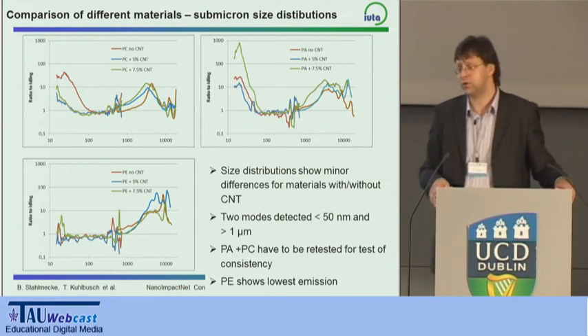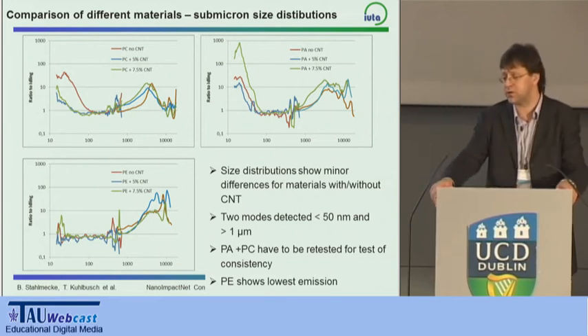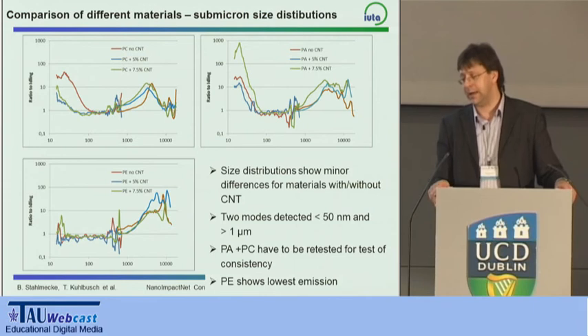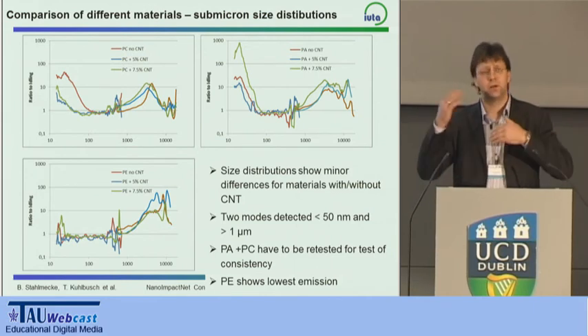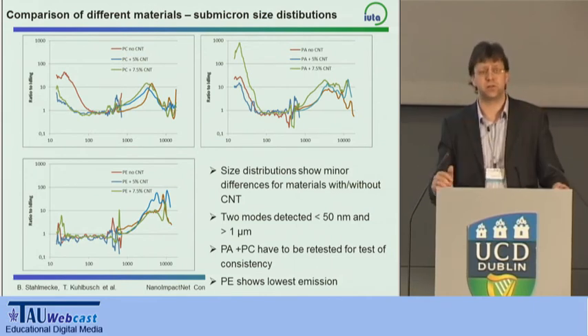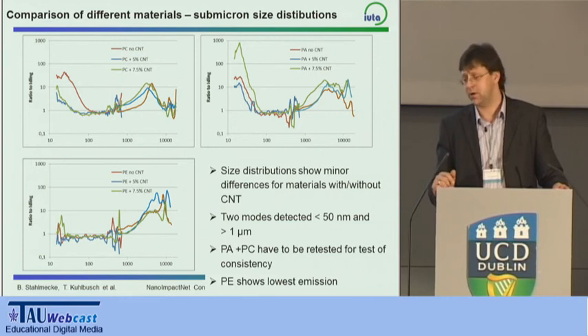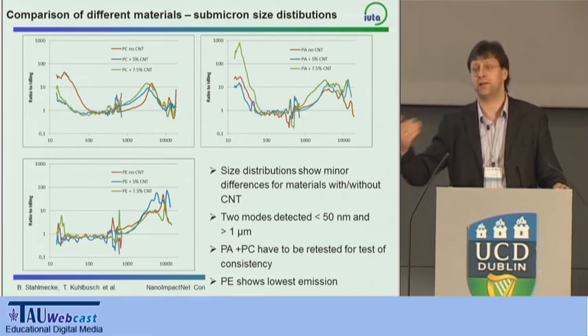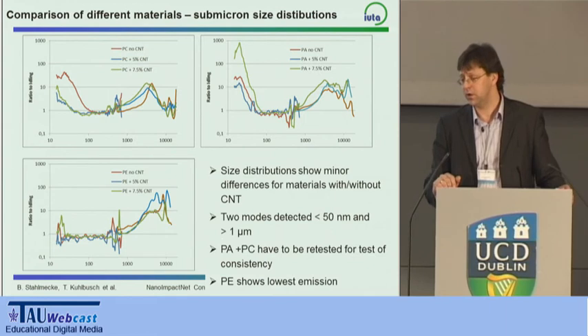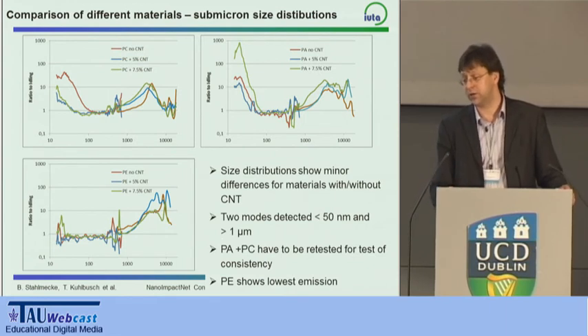We have always 2 modes detected, below 50 nanometers and above 1 micrometer. And certainly within the differences we see between the materials, we want to check and recheck again with some new production of polyamide and polycarbonate material to see whether we get the same results if we get a different batch of material delivered to us again from the company. And interestingly, polyethylene didn't show any sub-micrometer emission range of particles.